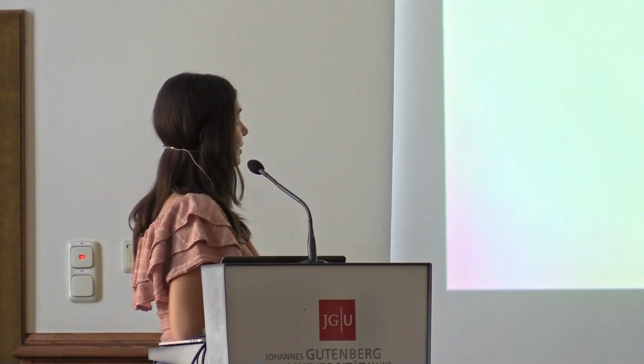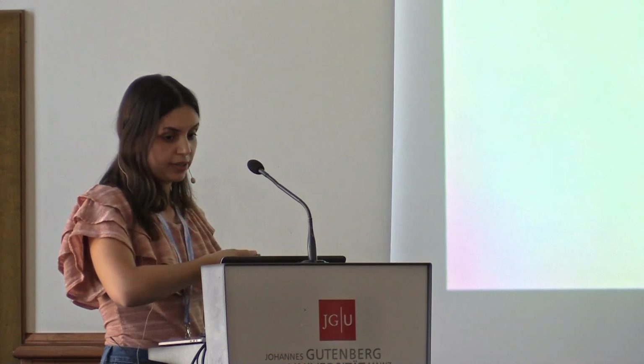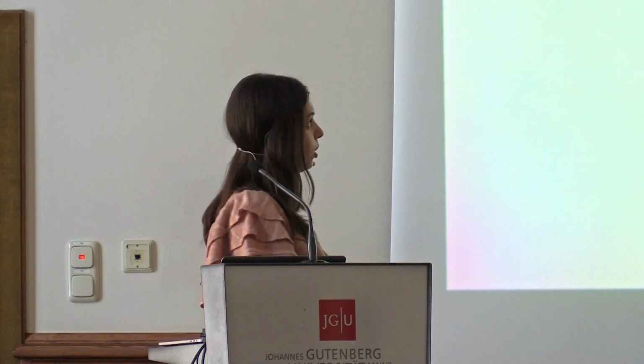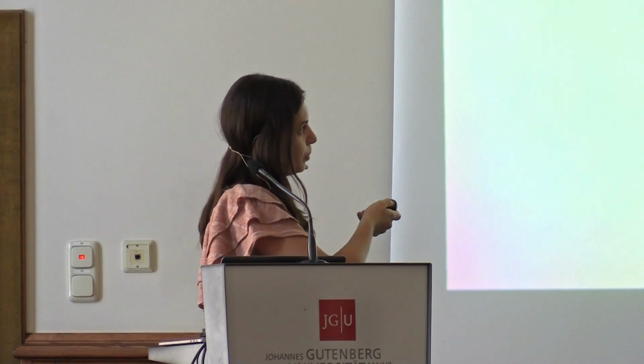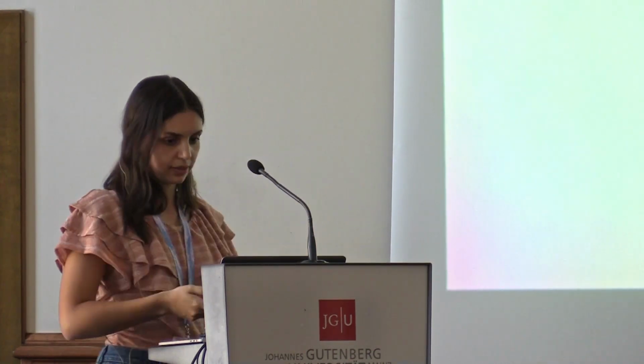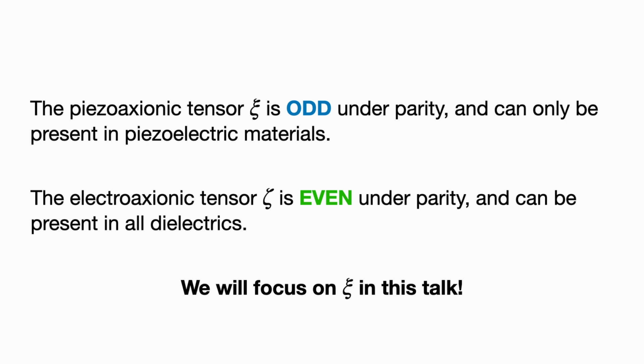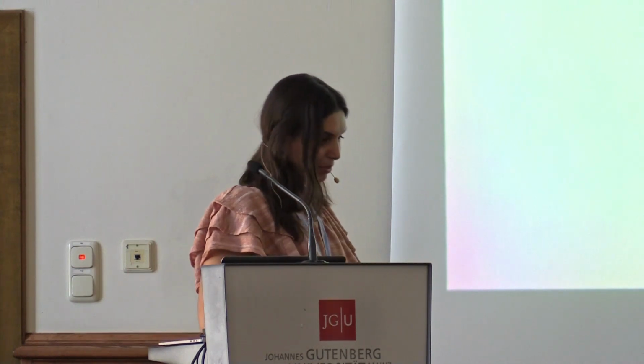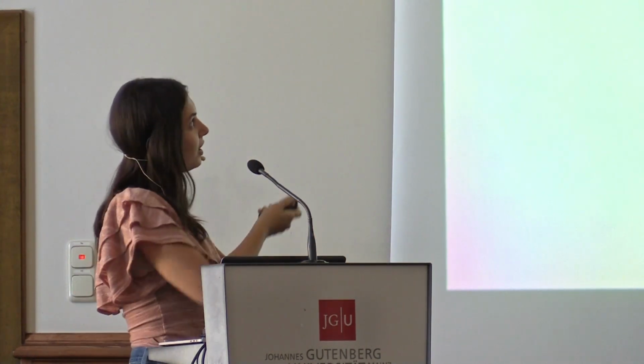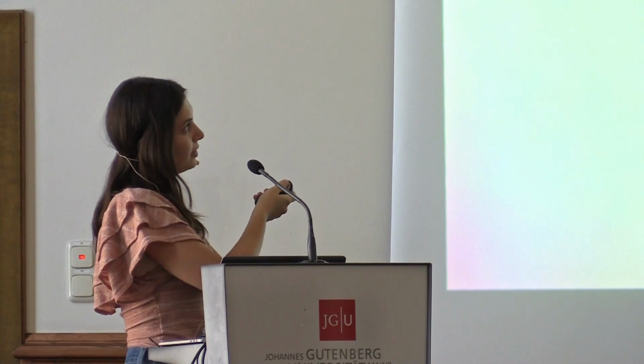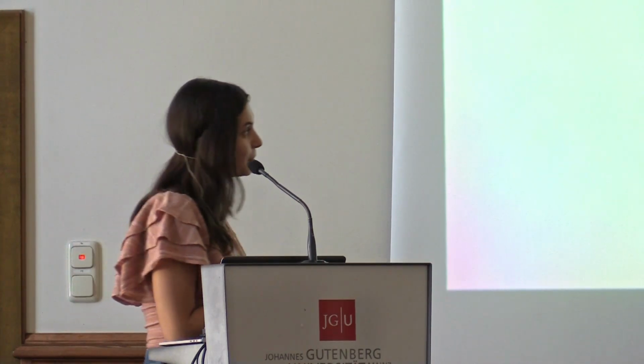So to summarize that previous slide, the piezoaxionic tensor is odd under parity and can only be present in piezoelectric materials, whereas we could also have an electroaxionic tensor which would be even under parity and could be present in all dielectrics. But as you can tell from the title, I'm going to focus on the piezoaxionic effect. And that may seem odd at this stage, seeing as it seems that a larger class of materials would have an electroaxionic tensor. And I will hopefully confirm to you at the end that in fact the larger effect is the piezoaxionic effect, because that effect is resonantly enhanced.